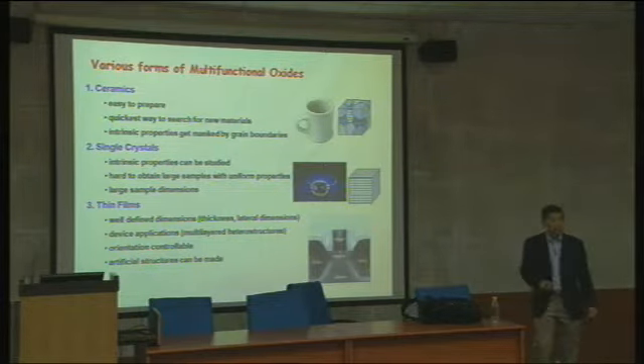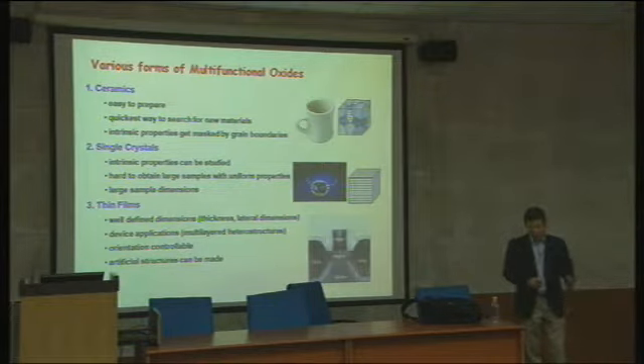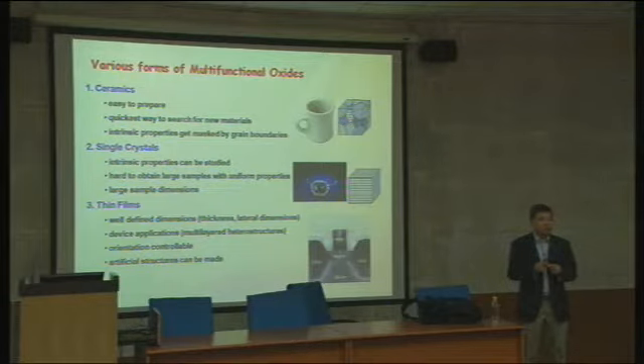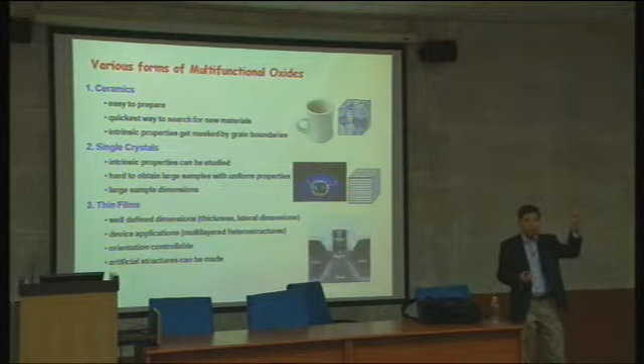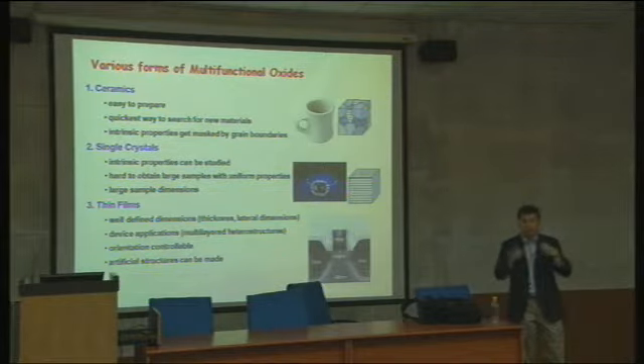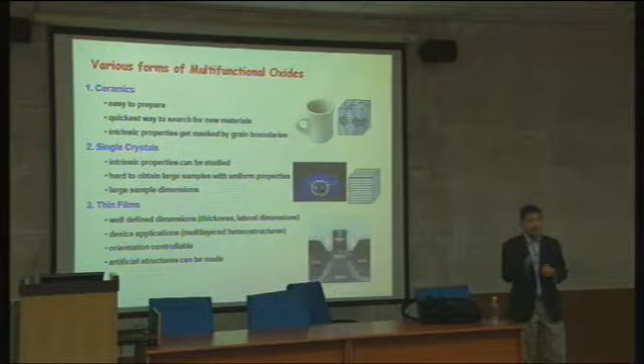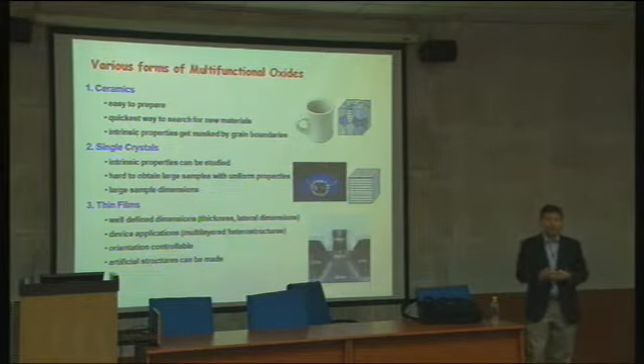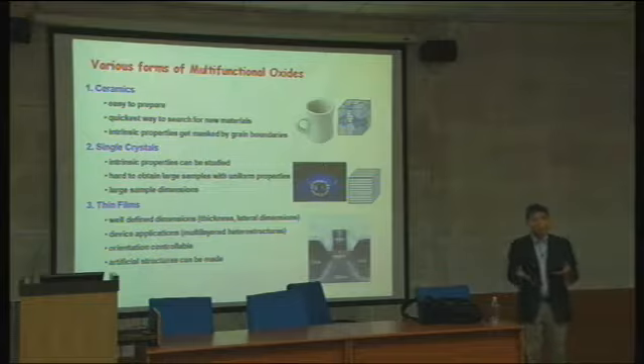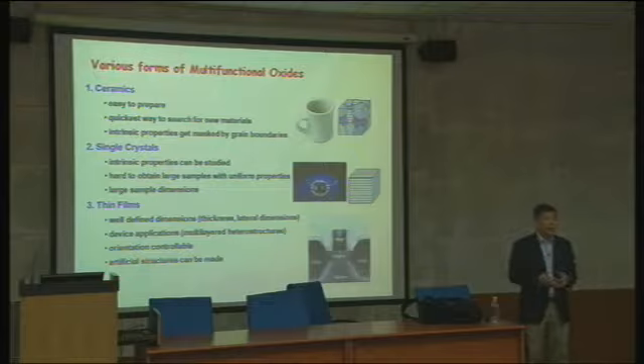And finally, thin films can make artificial structures, and there are two reasons why. First, when you grow single crystals, you heat up to the melting point, and growth of single crystal from the melt is an equilibrium process, which means you cool down very, very slowly, so atoms have enough time to move around and reach equilibrium. That means your phase is what we call an equilibrium phase, which you can see in the phase diagram. All the phase diagrams are equilibrium phase diagrams. But in thin films, you grow at a temperature a lot lower than the melting point. For example, strontium titanate melts at over 1,000 degrees C, but we can grow single crystal strontium titanate thin films at as low as 500 degrees Celsius.